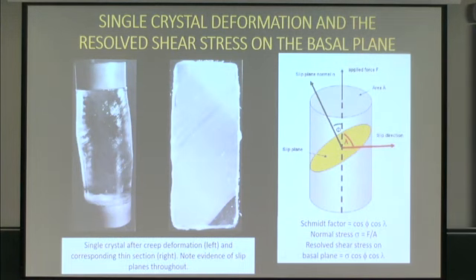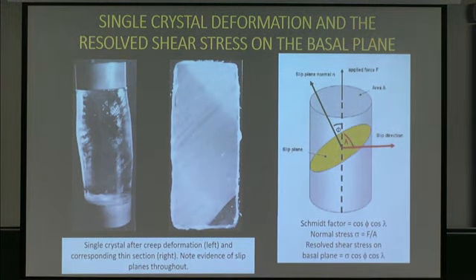Okay, so let's start at a single crystal behavior just to get you going. Erland showed you a couple slides about the atomic structure of ice. What we have here is actually a single crystal with the shear planes, the basal planes, at about 45 degrees to the loading axis here. And so the way we describe it, you have this very strong preference for deformation on those planes. We call them basal planes. And it is so strongly preferred to deform there, you can just view each crystal as deforming like a deck of cards. They really aren't going to do anything in other directions. Basal sliding is the name of the game. That's what the model is predicated on.